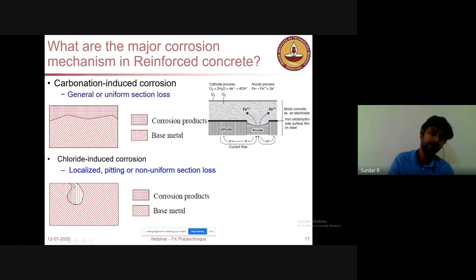There will be an increased concentration of chloride at this juncture. The chloride will come through the concrete and then reach the steel level. When the amount of chlorides present at the steel level increases to a certain level, that can initiate corrosion, and then it will go on and create higher mass loss. Due to that, the failure will be sudden. So when you are working in zones prone to chloride-induced corrosion, you should be careful about it, and you should make your concrete so dense that chlorides shouldn't penetrate.